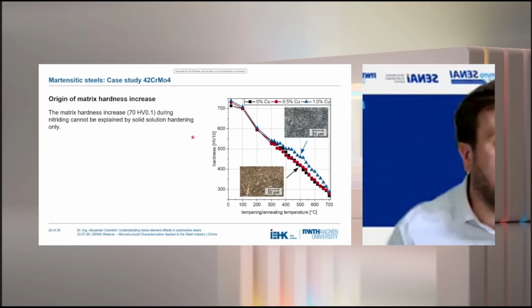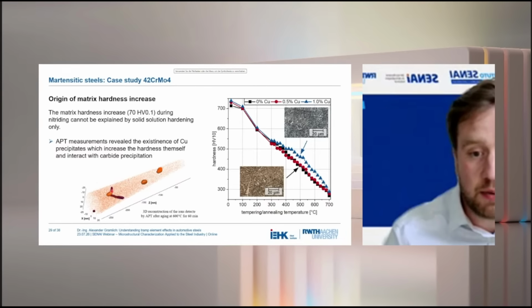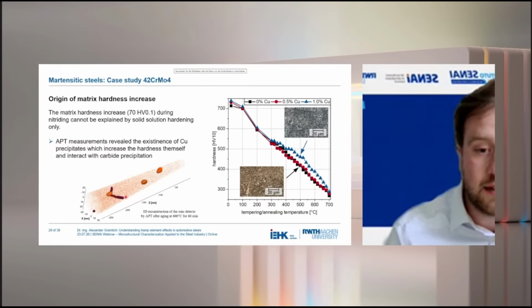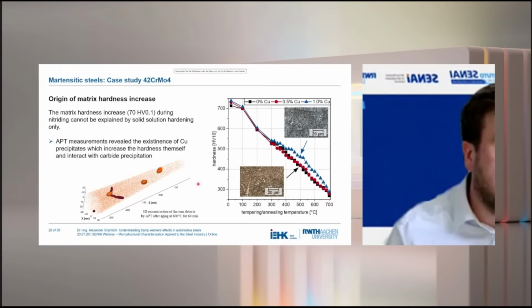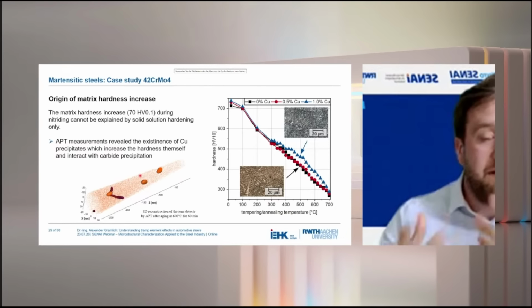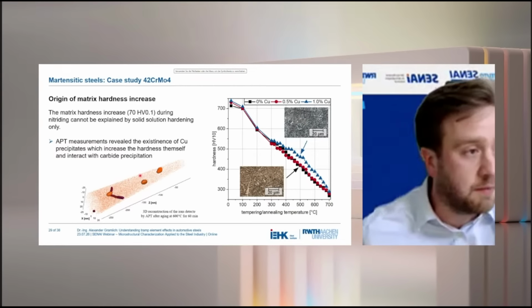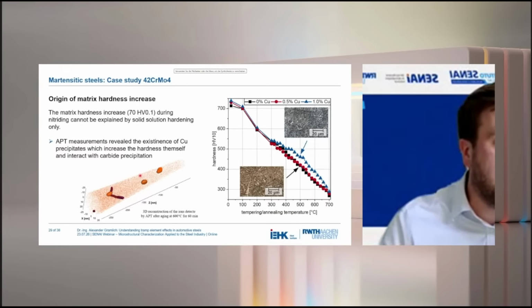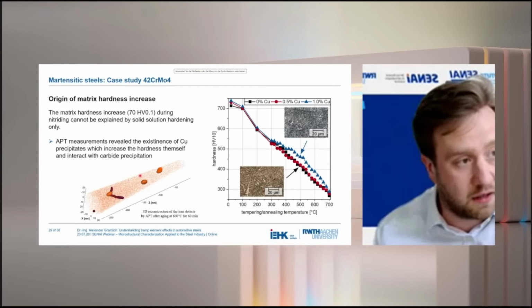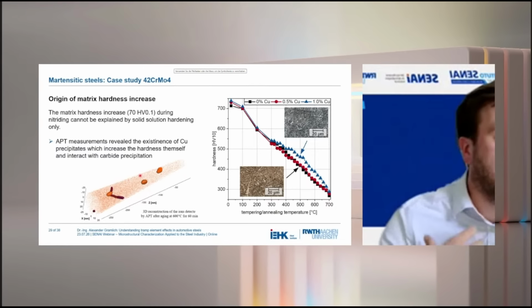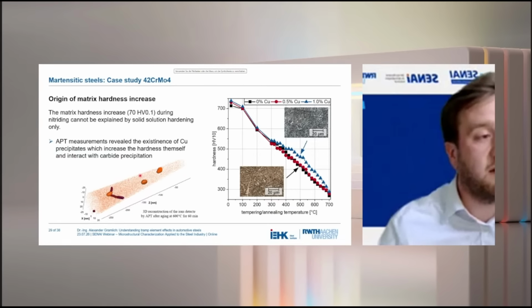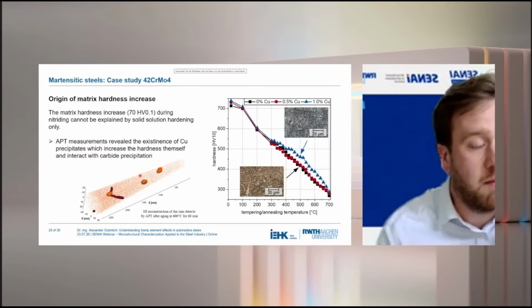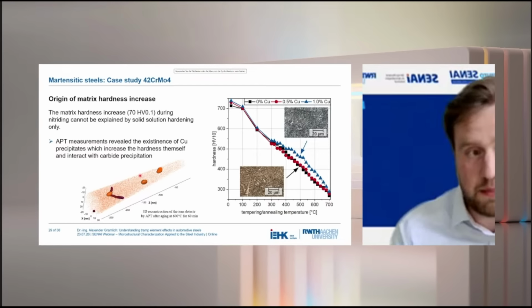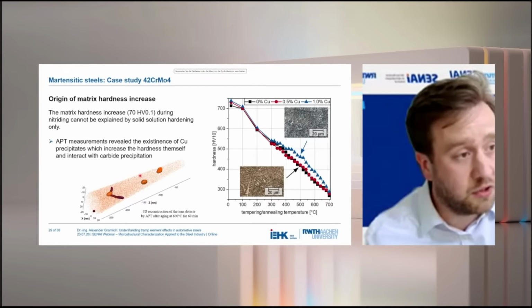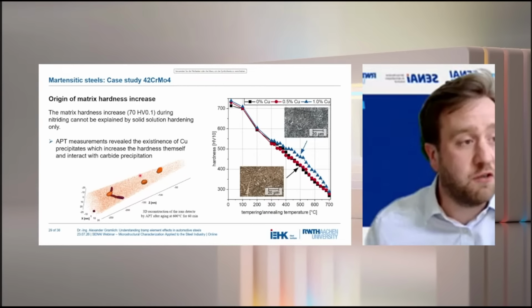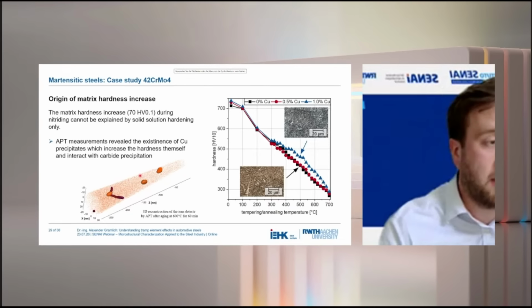But what we found when we looked into APT again is that the copper, here again in orange, connects up with cementite and other carbides. So the effect here of copper is not only that it adds by solid solution hardening, but it also interacts with the cementite and the other carbides, and more or less helps to keep them smaller, which is then effectively increasing the hardness more than it would be by solid solution hardening only. So you see here a lot of interactions which have to be assessed, combined, to get the full picture.